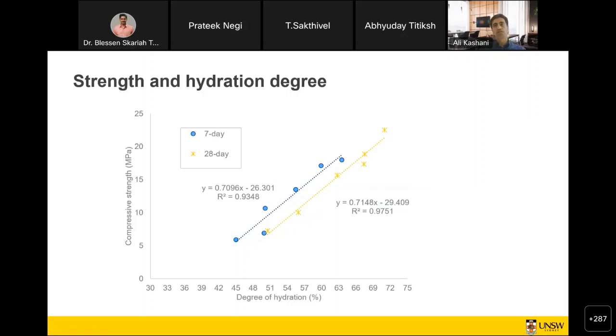And also the compressive strengths of the samples depend on the degree of hydration, because we have hydration and carbonation happening at the same time. So there is a balance between these two. Based on the density, the hydration, and other factors, the compressive strengths of the samples are going to change. So we need to keep a balance between these two.